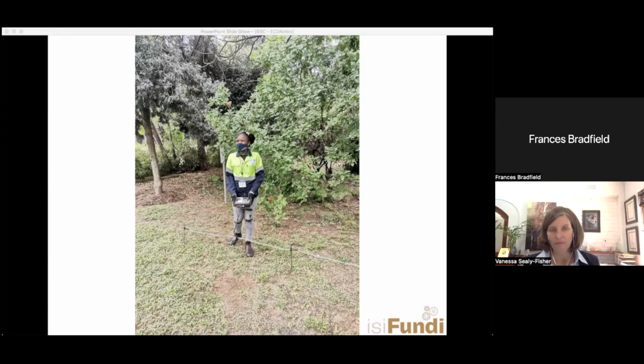And if we can use that, we look at it practically, we won't have much corrosion at all going on in that kind of location. And not only will digs be extremely difficult up there, it's very remote, all these kinds of things, it would probably not be necessary because of this very high resistivity. So something incredibly simple that's done at the very beginning of a project, maybe not even by corrosion people, maybe only by the geotechnical guys, really can be useful. And that's something, again, within our pre-assessment, you might be surprised that you could find this data from the initial geo-surveys for the pipeline. But again, it's a nice additional survey to help you make your decision if you're sitting on the fence between two locations.